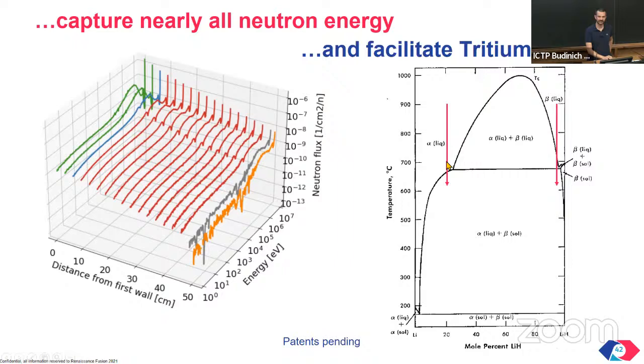Inject the liquid metal at 700 Celsius in the device. Under neutron bombardment, it warms up to 900 Celsius. You extract it from the stellarator. Before re-injecting it in the stellarator, you want to remove the heat, which you do by heat exchanger. Basically, you cool it down. In the process of cooling it down, you can also extract the tritium.